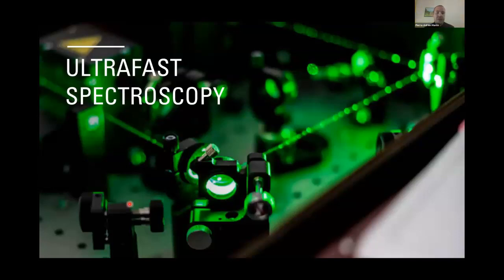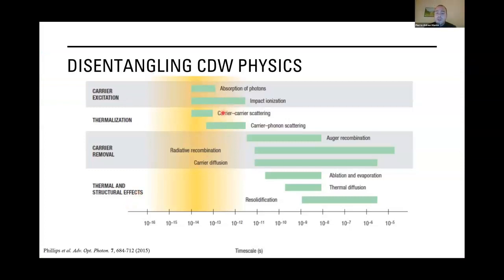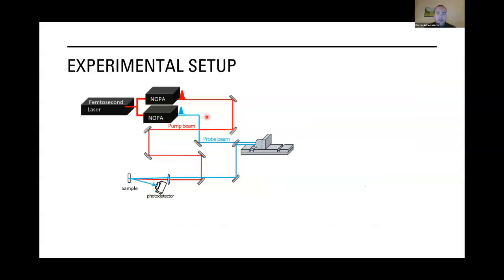So first, ultrafast spectroscopy. Like I mentioned in my first slide, charge density waves are often associated with a periodic lattice distortion, so it's difficult to separate the response from the electronic system and the lattice. For this reason people are using ultrafast spectroscopy, because when you excite your system, you are going to have a series of events that are going to occur. And usually the electronic system will respond on a much faster timescale than the lattice, so we are able to dissociate these two responses. To do that, we use classical pump probe spectroscopy.